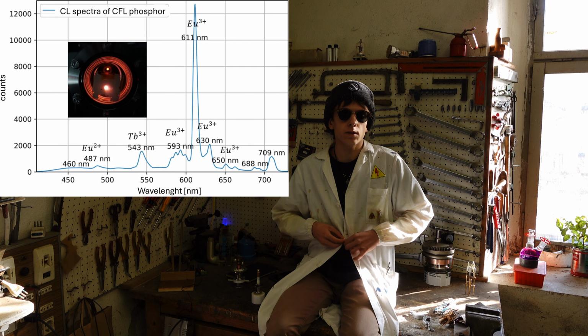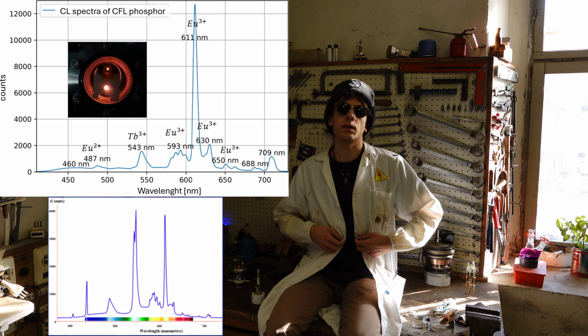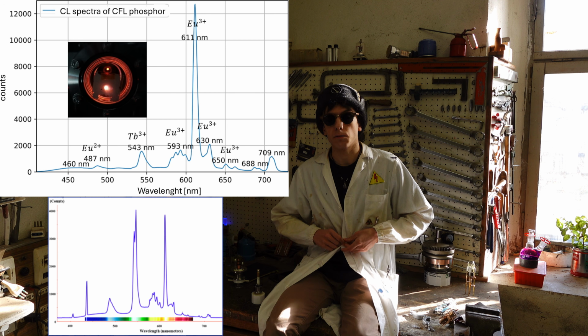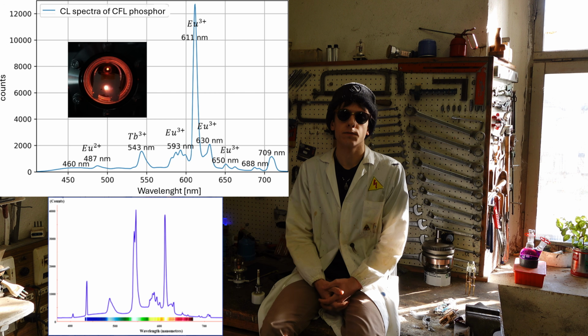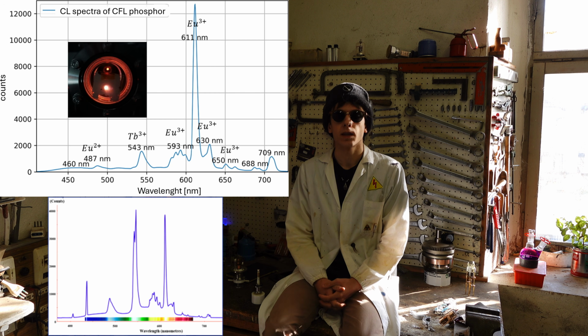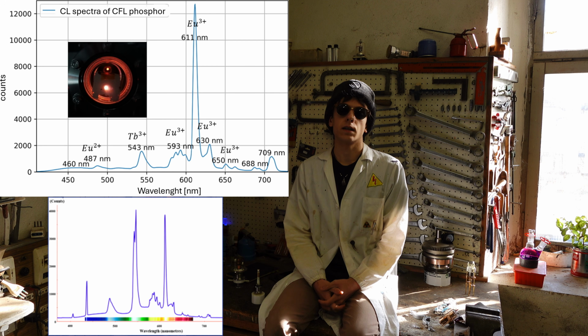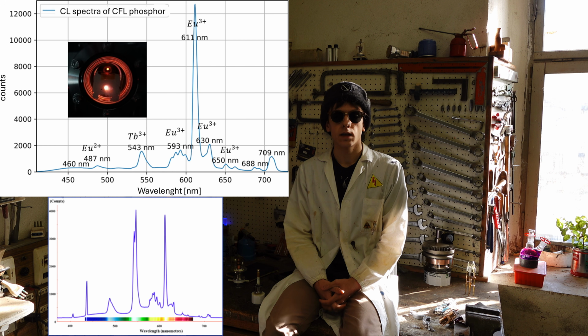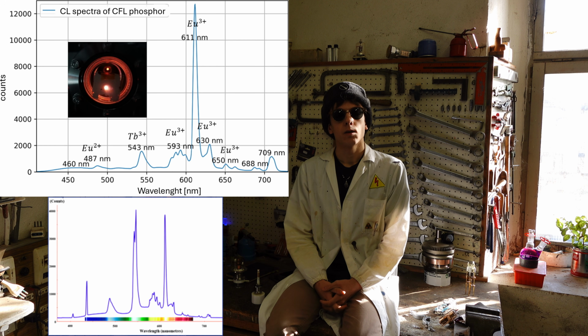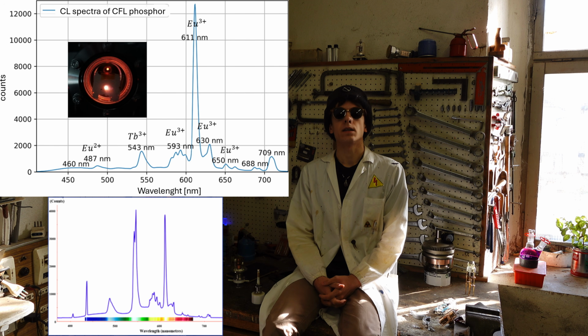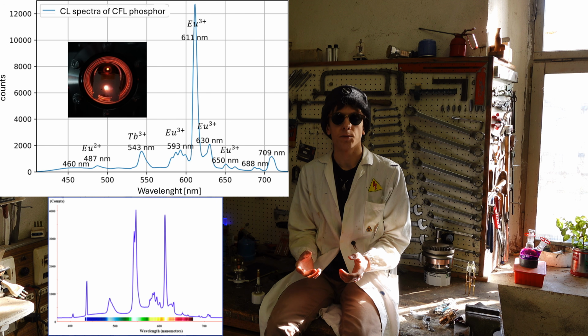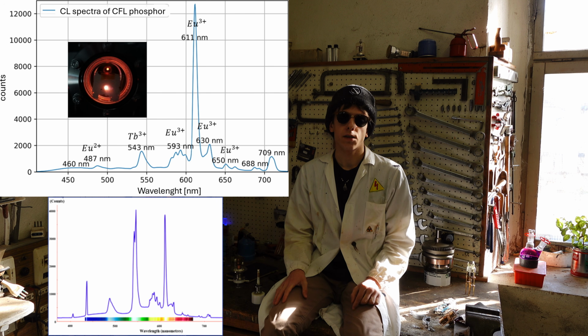We can also compare this with the spectra obtained by UV irradiation, and we can see a shift in the relative height of the different peaks. This results from the fact that extremely high energy electrons excite every atom equally, while the less energetic UV irradiation only excites some of the energy levels of the rare earth atom.